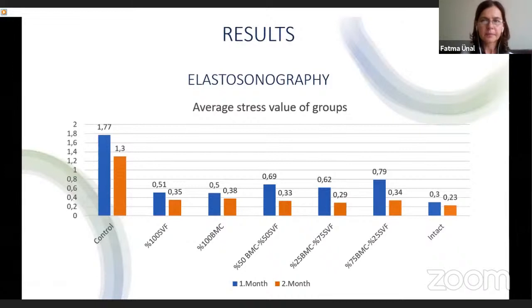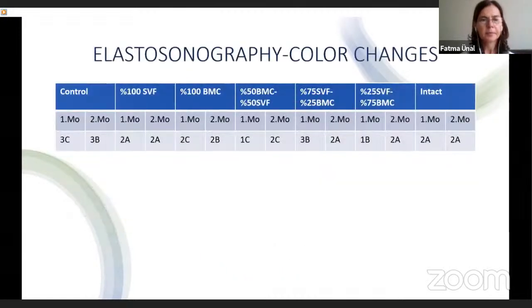When we look at the elastosonography strain value results, it is seen that individual use is better in the first month. But in the second month, it was seen that the 6th experimental group, with 75% BMEC and 25% SVF, showed the best recovery, and we saw that the mixtures recovered faster than individual use. Then we look at the elastosonography color change results. Although all groups tend towards a more homogeneous and flexible structure, the biggest change is again in the 6th group.